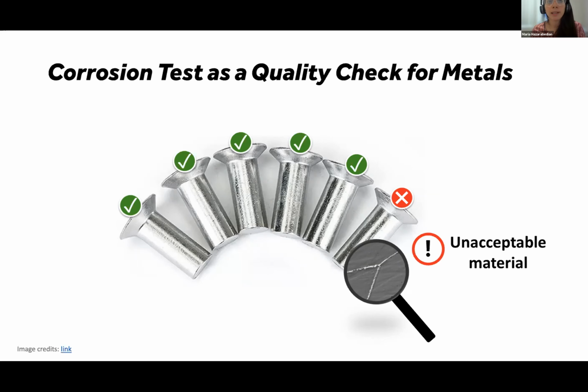My project aimed to develop a test that can simply detect batches affected by the precipitate. To that end, we took advantage of the fact that the precipitate can decrease the resistance to a type of corrosion called intergranular corrosion. Therefore, we propose to develop a test that can quantify the susceptibility to intergranular corrosion. And the higher susceptibility we measure, the higher the extent of the precipitate the material has. The challenge was to find the right conditions that can lead to intergranular corrosion produced by the precipitate. To optimize the condition of the test, we compared the performance of two types of samples. The first type were a set of batches that failed in service due to this precipitate.